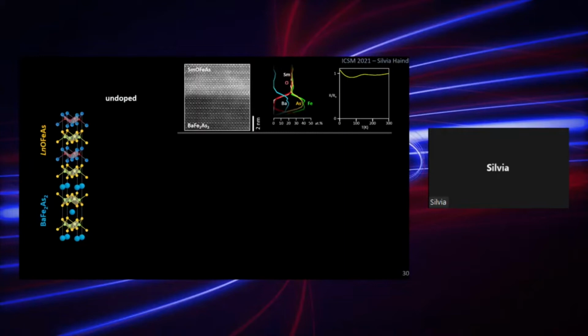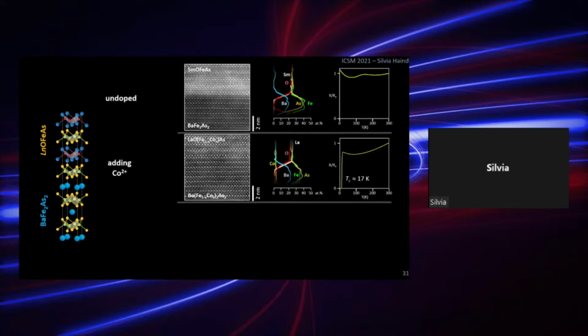So we can now test the stability of this interface by adding impurities, and we have done that by adding cobalt cations or oxygen anions. When we add cobalt cations, so cobalt 2 plus, into the target material, we have started the growth with the cobalt-doped iron oxypnictide target. We grow again this bilayer on top of undoped barium 122. We again find that the interface structure is clean, and we have a smooth and very sharp interface at the common iron plane. So the cleanliness of the interface stays intact.